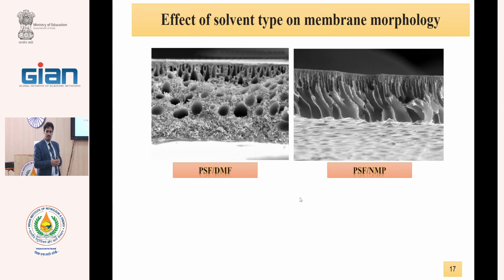So how can one be assured about the binding of the 2 layers? When we cast the second layer, for example, on a solid polymer, the solvent of the second layer can dissolve the support layer and produce an adhesive.